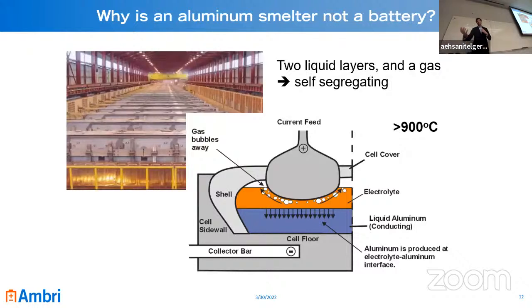And so one place to start is to ask, why isn't an aluminum smelter a battery? Why can't you not only put energy in, but also get the energy back out? One of the reasons is because of the way that the cell is configured. It has, as I said, a molten cryolite electrolyte, with liquid aluminum pooling on the bottom. And then during this process, you not only produce aluminum, but you also produce oxygen, which reacts with the graphite anode and produces carbon dioxide and bubbles away. So that oxygen and carbon dioxide isn't there to allow for the back reaction.